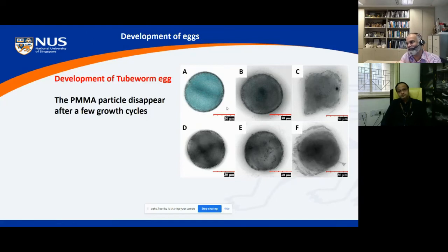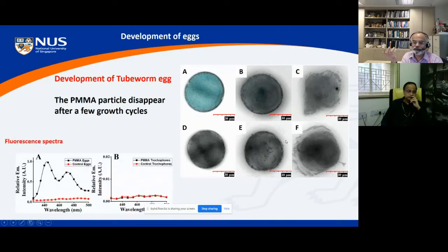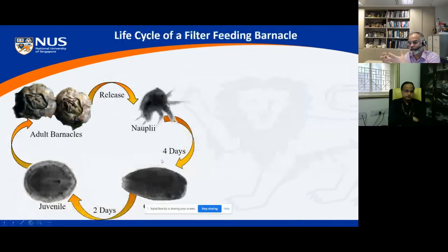So that is a kind of interesting observation we find in our studies. We still don't know the exact mechanism of how it goes out, but you can see after a few days, after a few growth stages, there are no more fluorescent particles. So this is the beginning of it, and this is after a few stages of growth, right? Once it grows up, then we don't see any more particles in the larvae as well. But we can also monitor that optically, because these polymer particles are fluorescent active. So we can see at different stages the PMMA inside gives you a very intense fluorescence, but control eggs have no fluorescence. And then we look at the animals which come out, and they don't have any more fluorescence, right? So they have a mechanism to eject these particles because it doesn't fit with their tissues or cells, right?